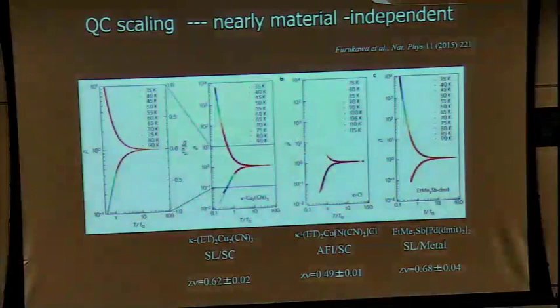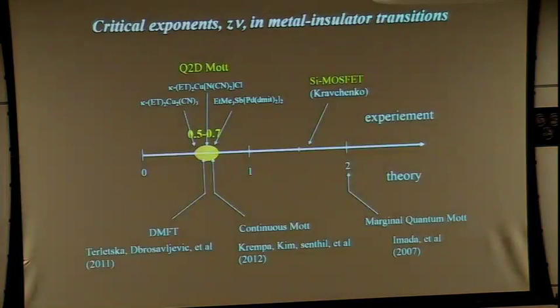For this material, the Z nu is 0.61, roughly 0.6 plus or minus 0.1. But I'm not sure whether this difference makes sense or not. It is likely that this difference is an experimental error. But anyway, this is a comparison of experimentally determined Z nu values and some theories. The continuous Mott transition and the DMFT calculations predict similar values.